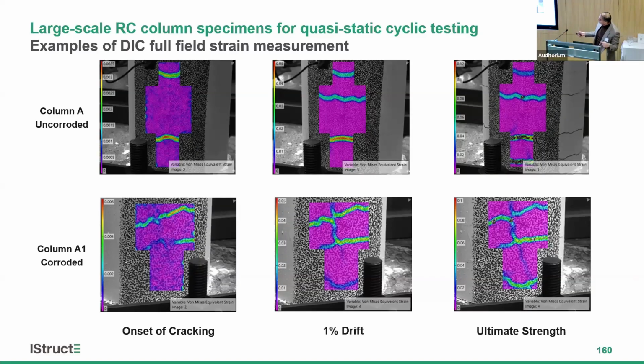So this is an example for column A, uncorroded. You see just classic flexure cracks, essentially horizontal, perpendicular to the direction of the loading. But when you have corrosion, we start getting this weird vertical crack, which is essentially because of the corrosion of the vertical bars. So even before we start loading, you get some vertical cracks. But as we load the structure, these cracks start opening up. So it changes the crack pattern.